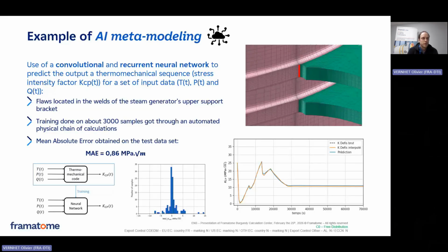So we got training data for 3,000 samples, and then we trained a convolutional and recurrent neural network with this data, and we tested our meta model on the test data, and we get quite good results on the test data because we get a mean error of 0.86 megapascal per square root meters. And you have here an example of curves that we got. You get in orange the curve we got from the chain of calculation, and in blue the curve that we had from the meta model. So you can almost not see the difference between the curves, meaning that the AI model is able to model quite accurately the physical chain of calculation. So instead of, say, several weeks or months of calculations, it only takes a few seconds to get the prediction through the meta model.